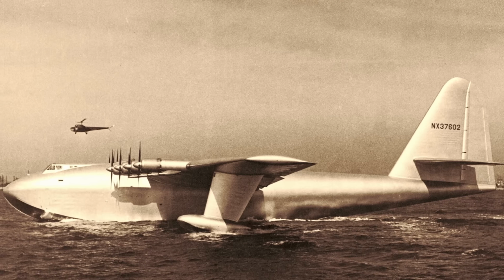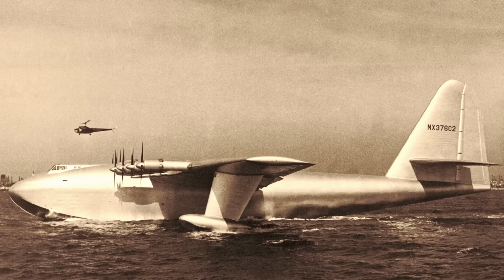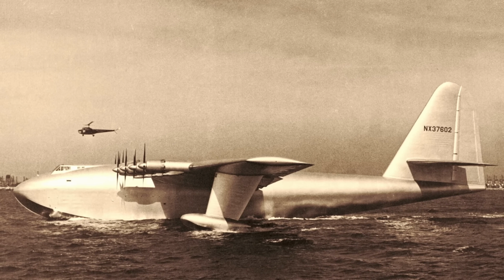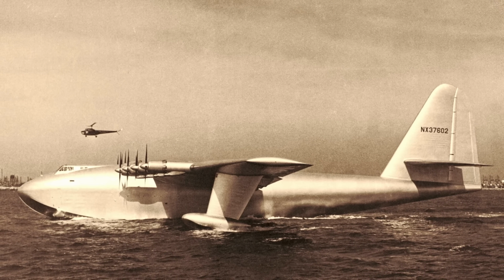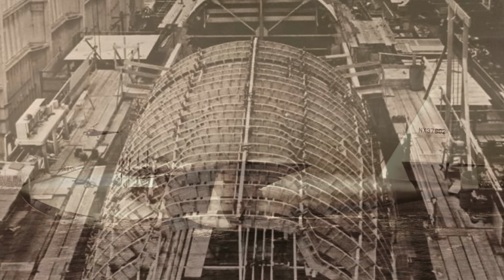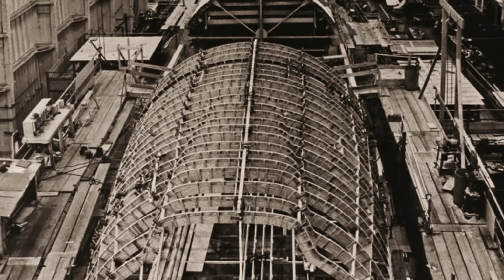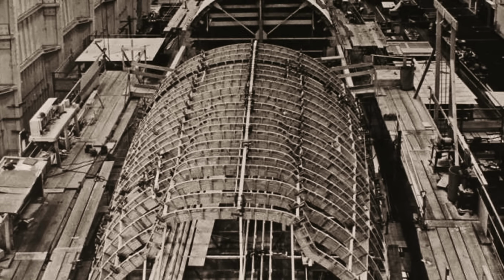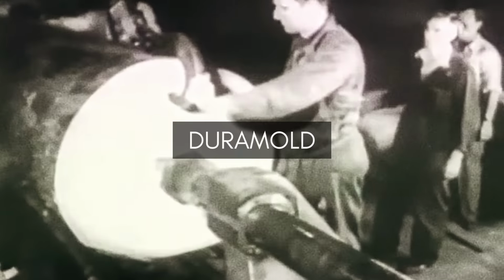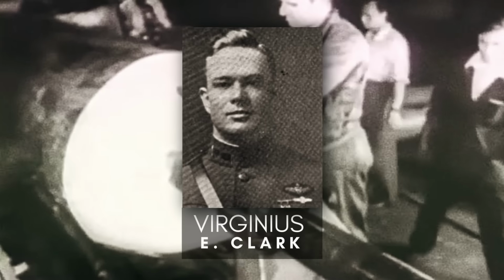Even more technologically ambitious was the Hughes H-4 Hercules. Referred to as the Spruce Goose, it was built primarily of yellow birch. In order to achieve the strength-to-weight ratio required for the massive aircraft without using restricted aluminum, a process known as Duramold was used. Developed by Virginius E. Clark in the late 1930s, the Duramold technique involves impregnating birch veneers, often as thin as 1/32 of an inch, with phenol formaldehyde resin.